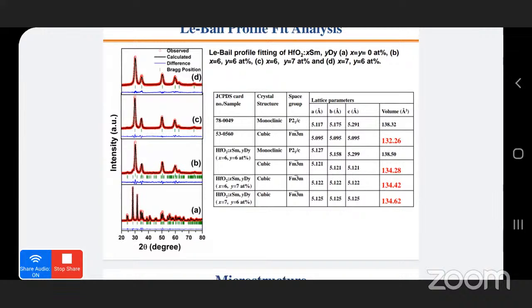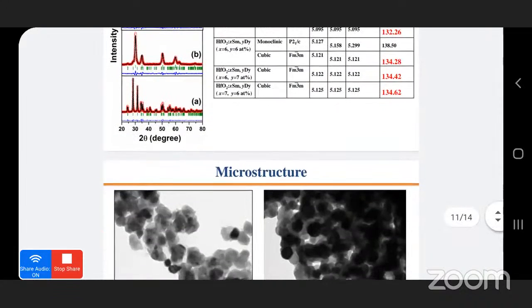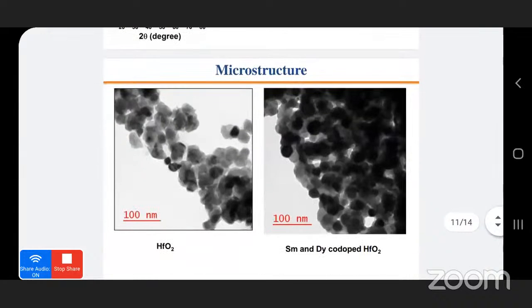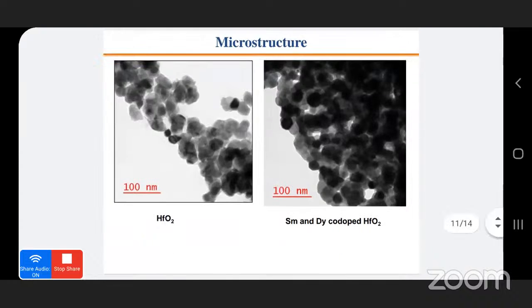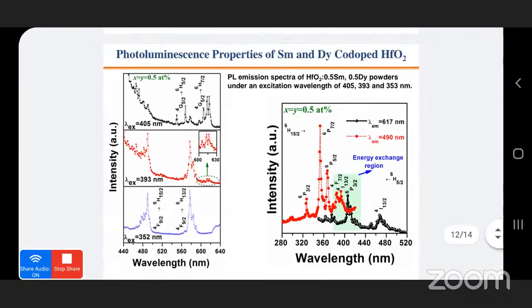So we can surely say that the dysprosium and samarium are responsible for the stabilization of the cubic phase at room temperature. So these are the microstructures of these synthesized nanoparticles. We can see for the hafnia itself, it is like 35 nanometer, and for the doped system, it is around 10 nanometer. So these are the PL photoluminescence properties, since we are using this rare earth element.